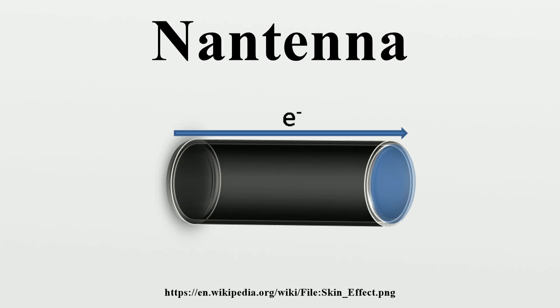An emissivity of 1 means the Nantenna absorbs all of the photons of a specific wavelength that are incident upon the device. Comparing the experimental spectrum to the modeled spectrum, the experimental results are in agreement with theoretical expectations. In some areas, the Nantenna had a lower emissivity than the theoretical expectations, but in other areas, namely at around 3.5 micrometers, the device absorbed more light than expected.